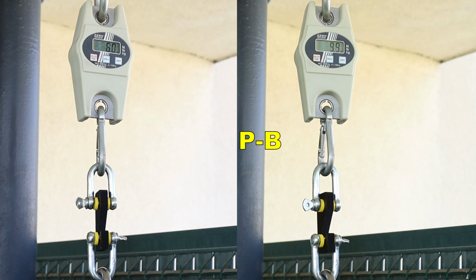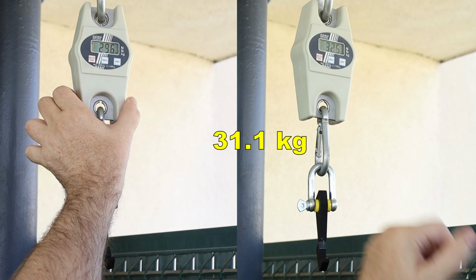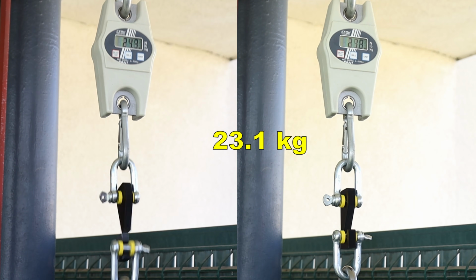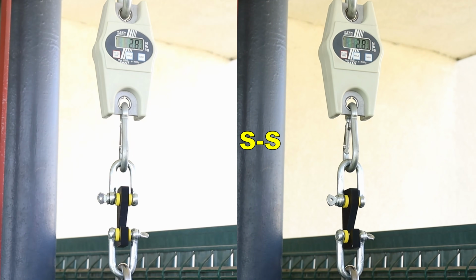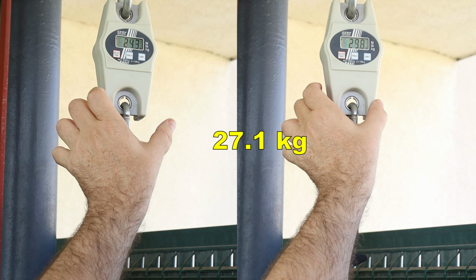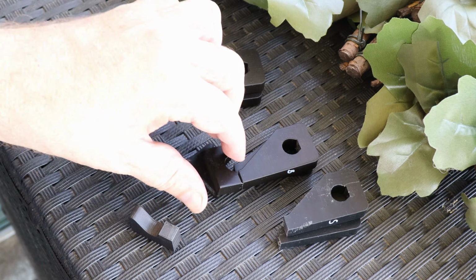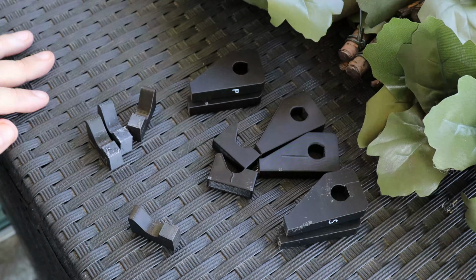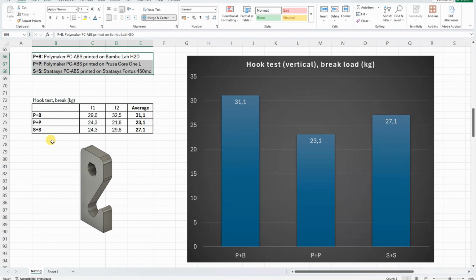These are hooks printed in vertical position. The layer adhesion is important here. Polymaker printed on Prusa. Stratasys. The break is very similar, only with the Bambu two parts are still connected. One more time, a reminder for this labeling, and interesting to notice that even if it was printed with some underextrusion, objects printed on Bambu Lab are stronger compared to the Prusa printers. Is this difference in the set temperature, or maybe those 30% part cooling are stronger on Prusa compared to the Bambu Lab? I'm not sure, but this is what I measured. Stratasys is somewhere between, and I'm very curious if we will see the same ratio on the layer adhesion test.